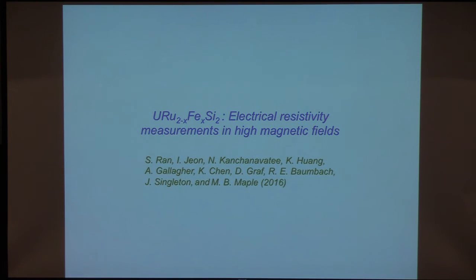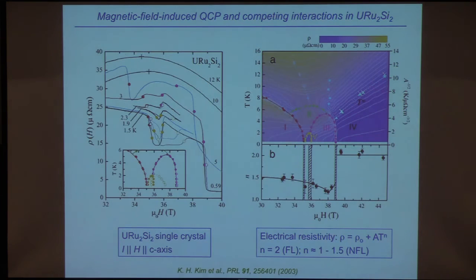illustrates the richness of the physics in this system, and that is electrical resistivity measurements in very high magnetic fields up to 45 Tesla at the National High Magnetic Field Laboratory in Tallahassee. This is earlier work done on pure uranium ruthenium-2 silicon-2, and this is resistivity versus magnetic field. These are just various features that you can pick out in these resistivity curves, which are quite complex. And then you can deduce phase boundaries in high field that look as indicated here.